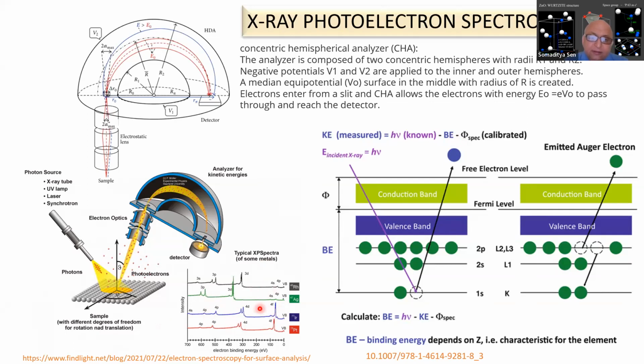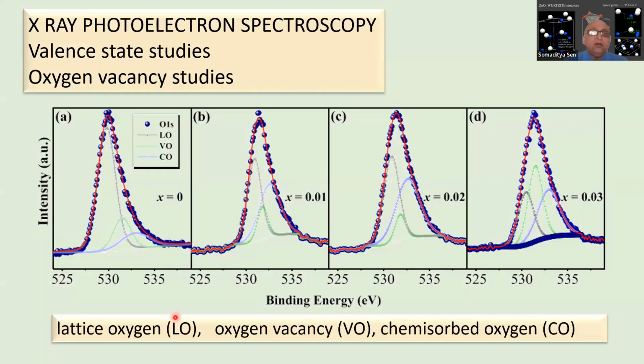So this is a typical graph showing the absorption of the energies. Where the binding energy is high, you can see there's a rise, so this binding energy is present. By analyzing these binding energies, you can find out, in this typical example which I show, there can be lattice oxygen in the material, oxygen vacancy, or oxygen which is chemically absorbed on the surface. Those components you can follow up and find how, if you chemically modify this material, this chemical modification has altered these components of oxygen in the oxide material. This type of thing can be well studied using X-ray photoelectron spectroscopy.